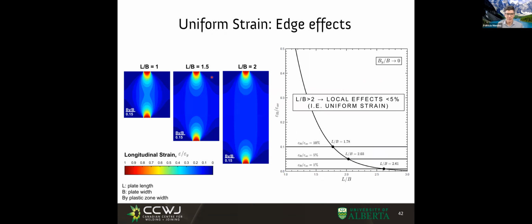One last thing that I wanted to show to you. In these calculations, I want to show you the effect of the plate length. When we use the concept of weld as a line, we assume that the line is narrow and long. But imagine a square plate in which the weld wouldn't be so long, right? The plate is too short to consider that the line is long. And what we see is this tension force in these edges causes some amount of strain, and this is what we call edge effects.